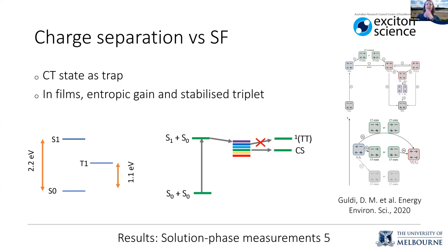Okay. So we think that that charge transfer state is acting as a trap, and I've tried to demonstrate it here. So if you imagine these different colors as being different solvents, by having different dielectric environments, we're stabilizing this charge transfer state so that it's below the correlated triplet there. And so then we rather have charge separation and we don't see singlet fission. And the thing about DPP is that these levels are very closely matched. So the triplet state is basically half the singlet. So there's not a lot of freedom, energetically speaking, to get around any barriers that might be present.